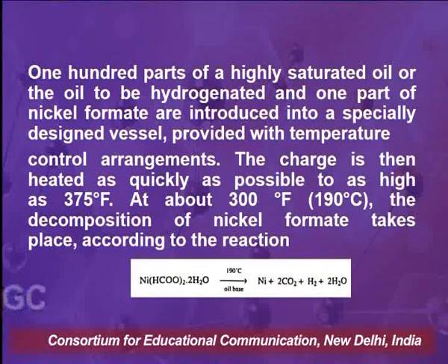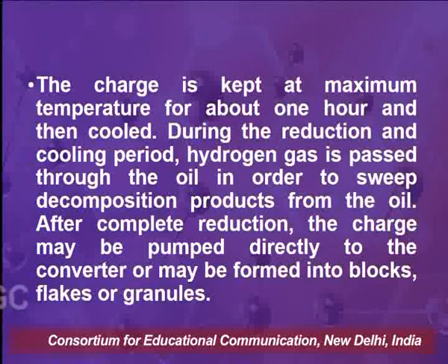The charge is then heated as quickly as possible to about 375 degrees Fahrenheit. At about 300 degrees Fahrenheit, the decomposition of nickel formate takes place according to the reaction shown here, and the nickel catalyst is formed. The charge is kept at maximum temperature for about 1 hour and then cooled.